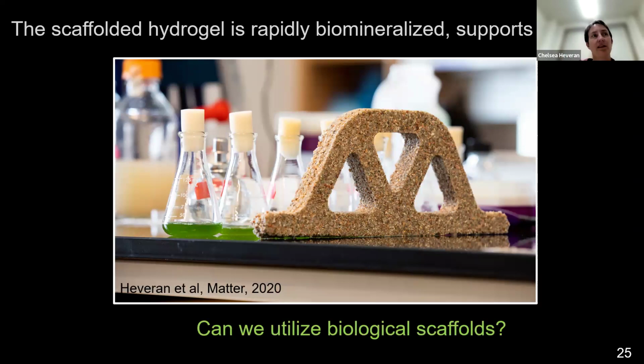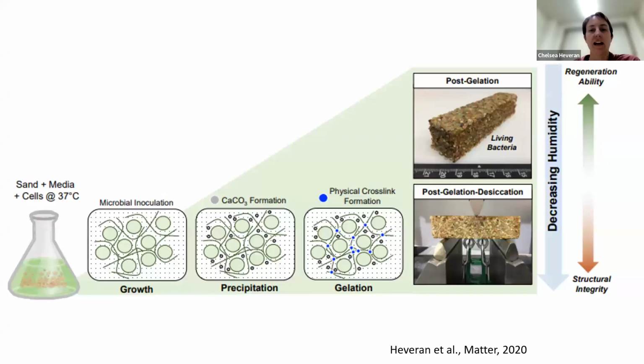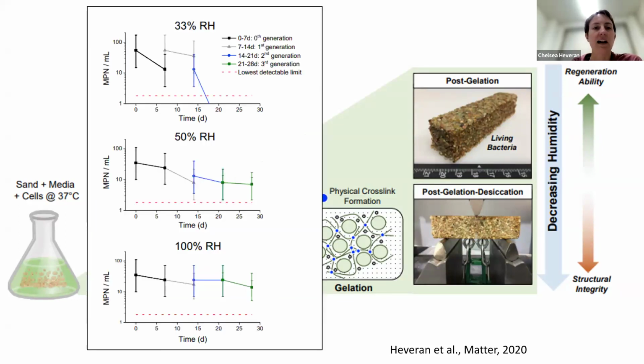And it was good for building things quickly. It was not as good for some other things. The hydrogel was not as robust to some systems. And we couldn't control, let's say, a lot of microarchitecture features about that hydrogel scaffold. It worked pretty well for us for what we wanted to do, though, and it was very exciting that we were able to keep cells alive in some conditions for a month. So if we kept the scaffolds humid, they lived for a long time.